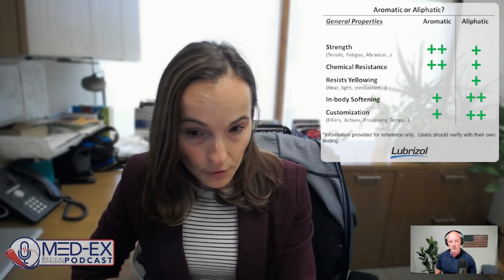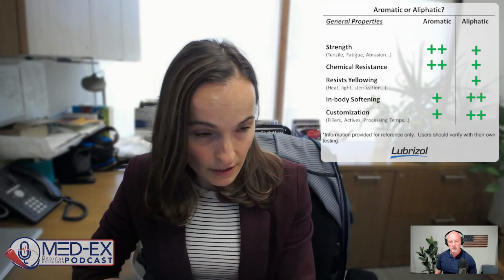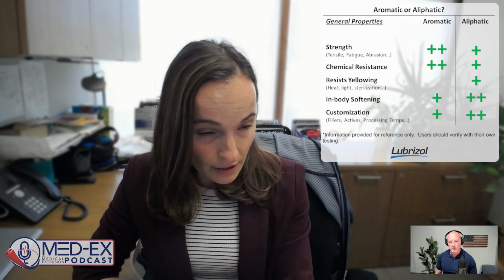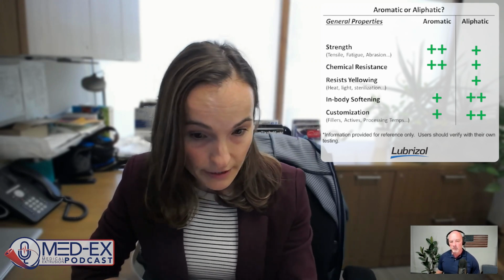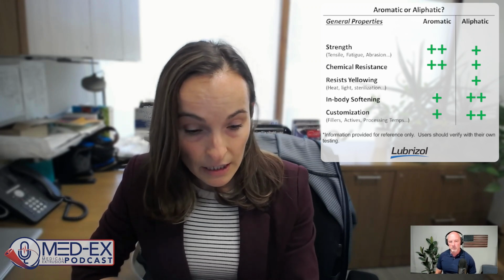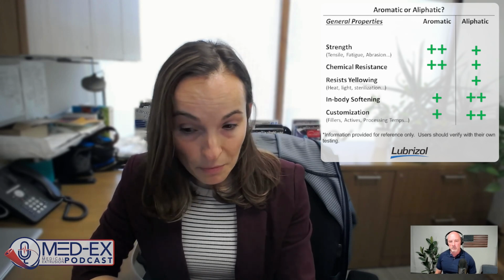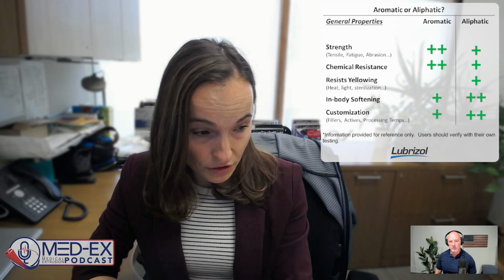With an aliphatic material, one of the main benefits is that it's a non-yellowing type of isocyanate. So you will maintain your clarity and your color much better, especially if you're planning on gamma sterilizing, for example, having exposure to radiation or UV light. The other thing to note about aliphatic is that it is a less tightly packed structure. So TPUs made of aliphatic isocyanate can actually soften more in the body, and you can see that as either a strength or a weakness, depending on the application.